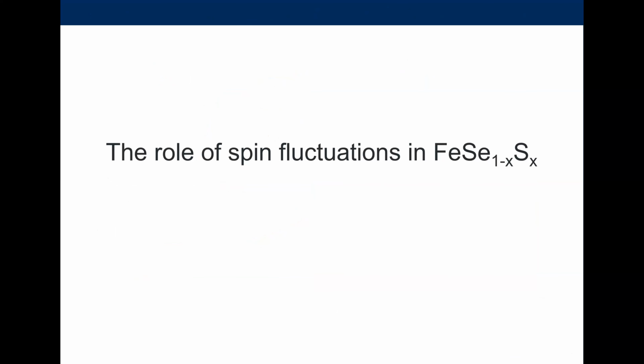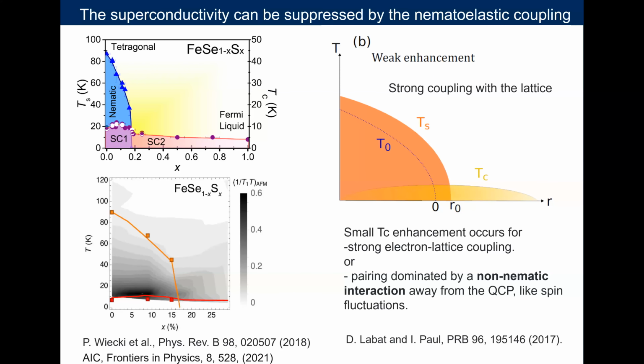And in the last few slides, I'm just going to summarize in a way the role of spin fluctuations in this family of compounds. As I said, NMR has detected that spin fluctuations are likely to exist inside the nematic phase, and they are likely to be responsible for its superconductivity. But the strong coupling with the lattice affects the critical fluctuation at the nematic endpoint. So why is superconductivity not enhanced here, as we usually expect if we have strong fluctuations?